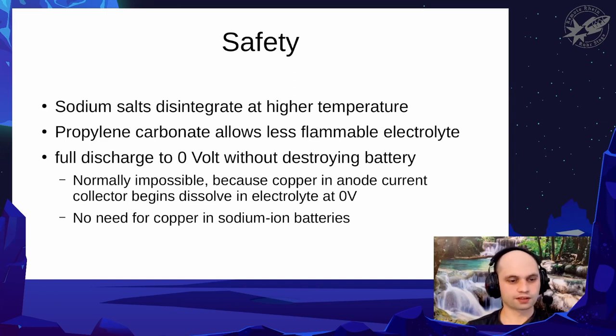Their batteries are also very safe. The safety of sodium ion batteries is in general much better than lithium ion batteries because the sodium salts disintegrate at higher temperatures. The salts are the first thing that starts to disintegrate when you heat up a battery. And the problem with that is there's fluorine in these salts, and the fluorine starts to react with the electrolyte around it, and it starts to